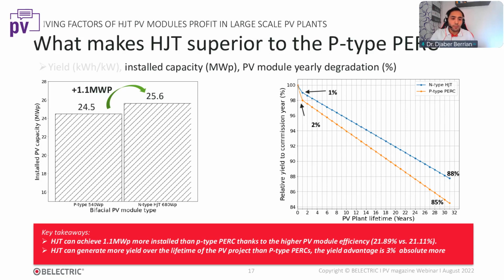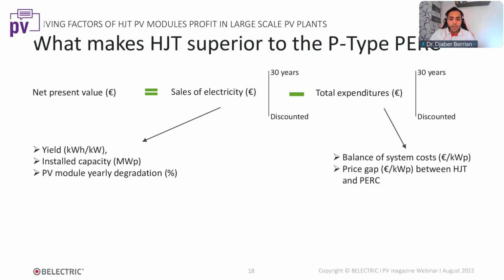This degradation is very important because it is usually overlooked by investors. Usually they use the yield from PVsyst, where this degradation cannot be seen. But when we take the degradation over time, we see that the yield gap between the heterojunction PV module and the P-type PERC PV module becomes even bigger over time, and this has a big impact on net present value. Just to mention, there are other factors which go into total expenditure, which I did not show here for time, where there is also an advantage for the heterojunction PV module, which are balance of system costs. They are lower for the heterojunction PV module, and also the price gap is a very important input, because it will have a big impact on net present value if it is different.